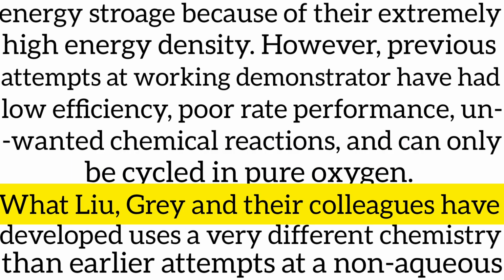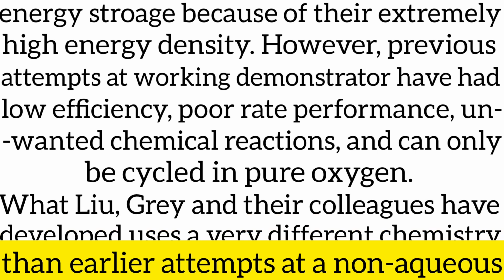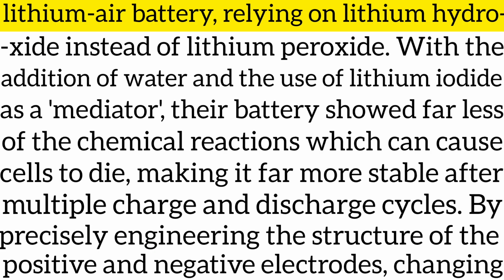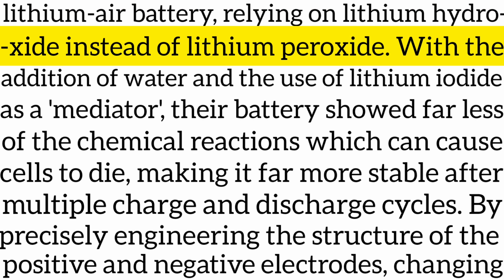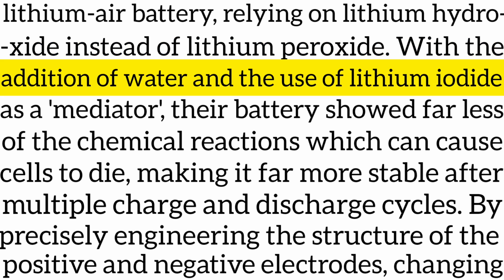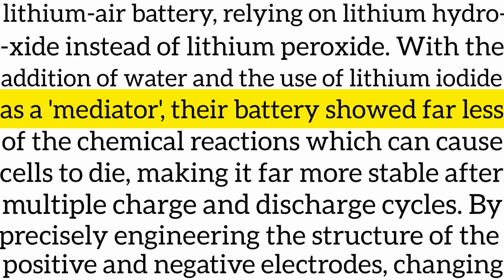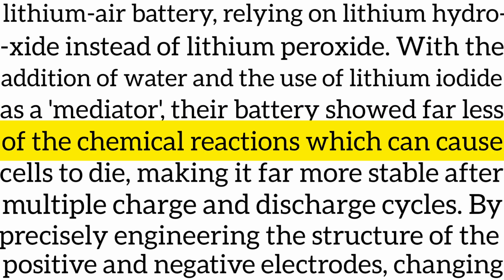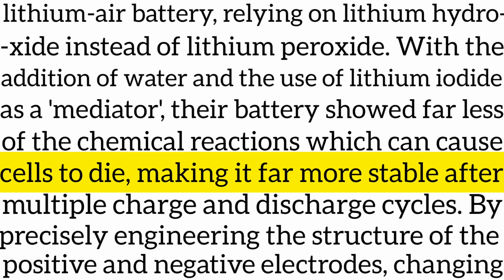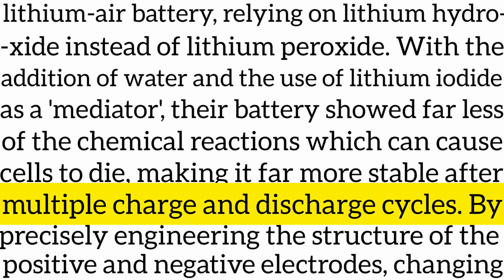What Liu, Grey, and their colleagues have developed uses a very different chemistry than earlier attempts at a non aqueous lithium air battery, relying on lithium hydroxide instead of lithium peroxide. With the addition of water and the use of lithium iodide as a mediator, their battery showed far less of the chemical reactions which can cause cells to die, making it far more stable after multiple charge and discharge cycles.